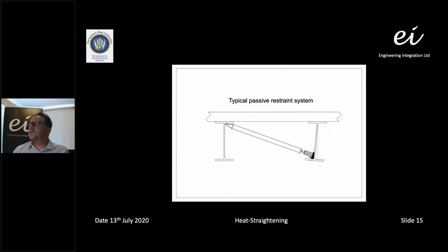When we talked earlier about providing restraint, this is how we would typically provide restraint, and this is passive restraint, so we're not providing any jacking force in the prop. We're just basically putting enough force in the prop to hold it there. We then heat on the outer face of the deformed girder. That tries to push and rotate the girder towards the left as you're looking at the screen. Obviously it can't because of the prop, but as the girder cools, it can move away from the prop and the prop becomes loose. And that's principally the principle behind heat straightening and the restraint that we provide.